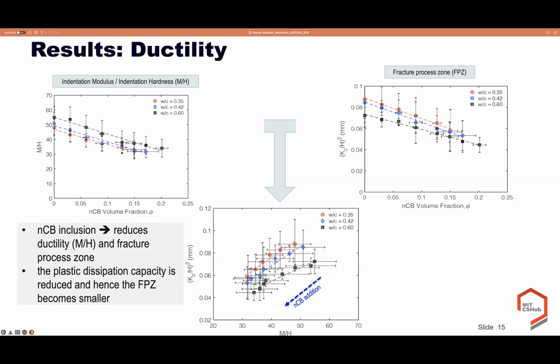This motivates us to eliminate the effect of nanocarbon black and link directly the fracture processing zone and the M over H ratio. The results show that it scales linearly with M over H, and the dashed line represents the regression model with R squared of 95 to 98%. The blue arrow shows the direction of increasing nanocarbon black content. This correlation shows that the plastic dissipation is reduced, and hence the fracture processing zone becomes smaller.